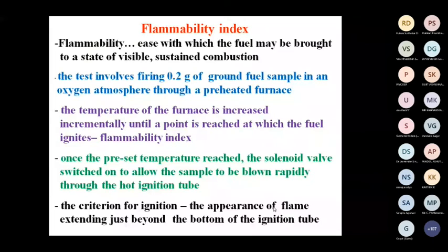Next one is the flammability index of the fuels. That's another characterization technique. Flammability means the ease with which a fuel may be brought into a state of visible sustained combustion. The test involves firing 0.2 gram of finely ground fuel sample in an oxygen atmosphere through a preheated furnace. The temperature of the furnace is increased incrementally until the point of interest is reached. The temperature at which the fuel ignites is called the flammability index. Once the preset temperature is reached, the solenoid is switched on and allows the sample to be blown rapidly into the ignition tube. The appearance of flame is the ignition point.